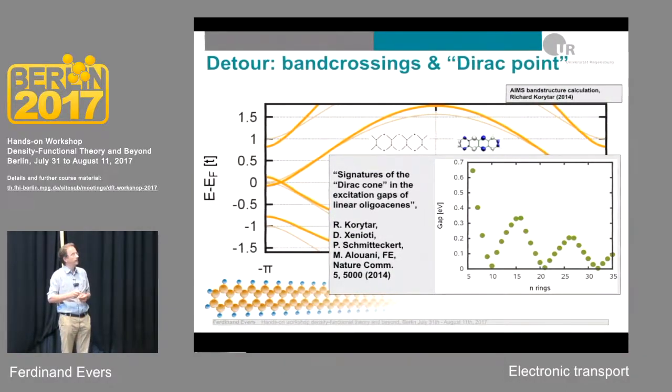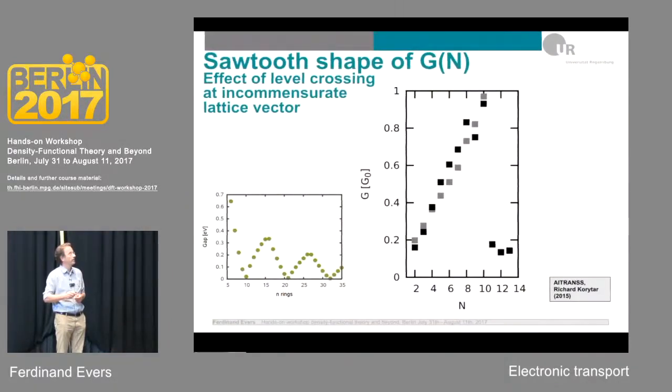So the prediction is, if you make the molecule longer and longer, the length should be about 10 or 15, or 10 or 12 maybe. Then there's a decay of the gap almost down to 0, and then it reemerges and it decays and it decays. So far we have just been touching with the experiment that I was discussing this regime, but not yet this regime. And the prediction is that if we would make this system much longer, due to this zone folding type of argument, we would find a conductance that goes like this. It goes here. Eventually it looks a bit like it will saturate. But then if you go further to even longer systems, then there is a cut. It drops sharply and you start again from 0.